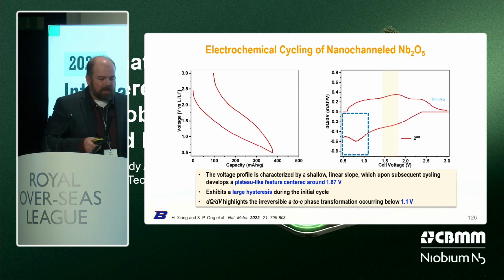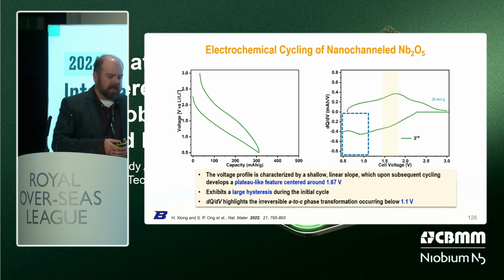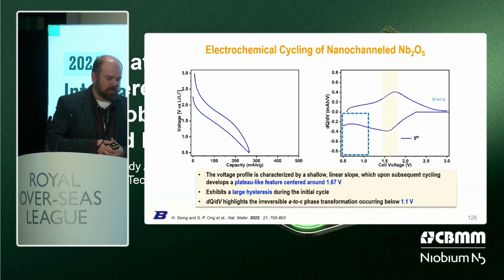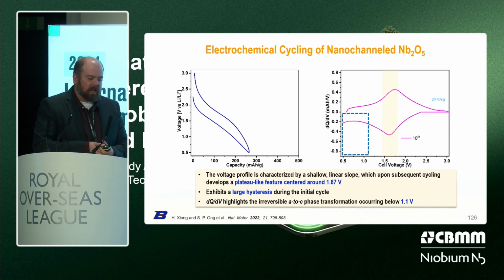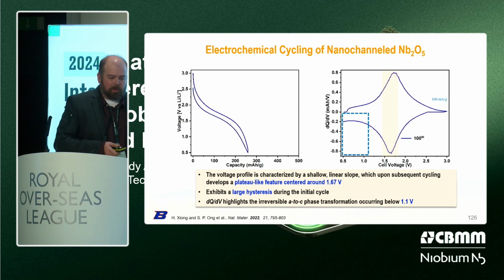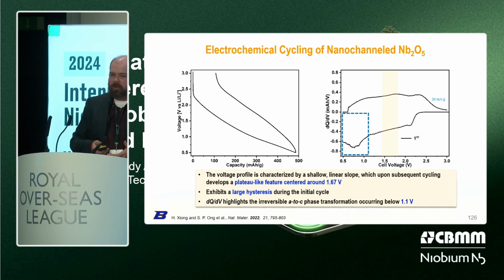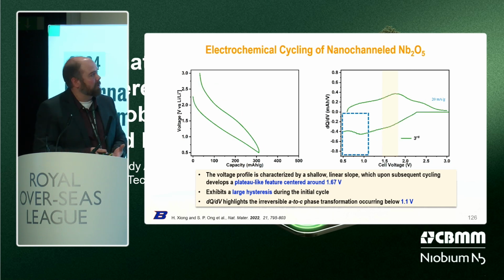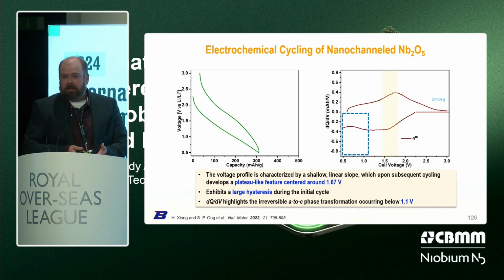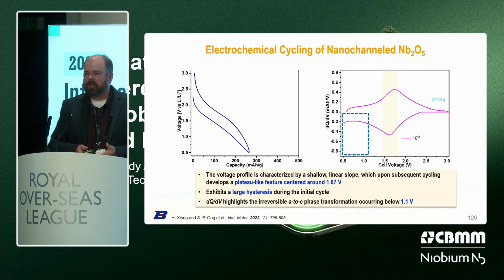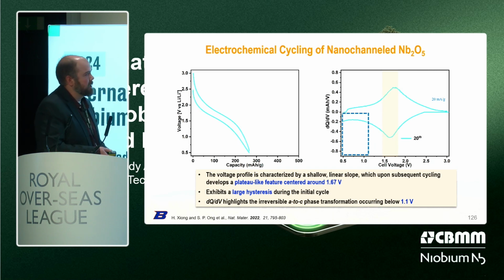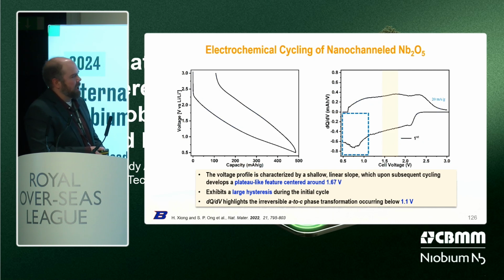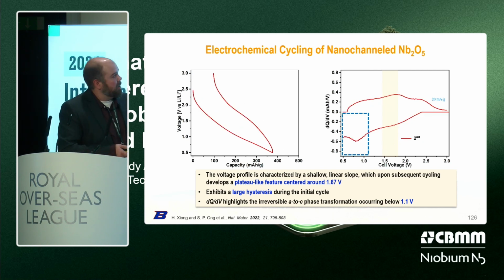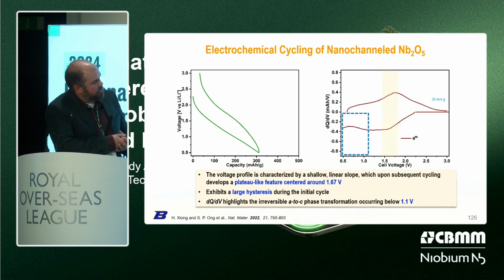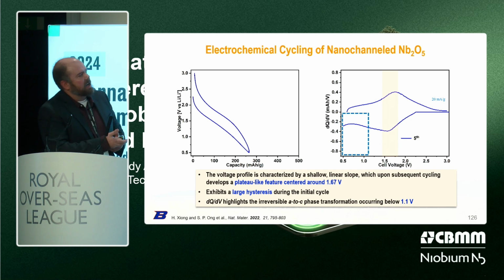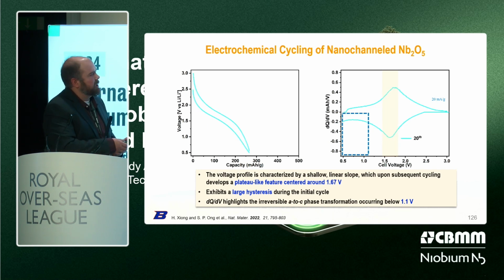Now, a cool thing happening here that you can see on the screen is a video playing that shows the voltage profile and also a dQ/dV, similar to a CV, right? A lot of you might be surprised because it's changing rapidly over time. Each cycle, the profile shape is changing. It actually goes from something that looks quite irreversible to something really reversible. If you pay attention below 1 volt at the first cycle, you're going to see a large hump in that region.